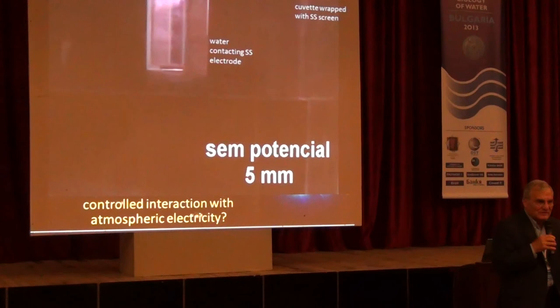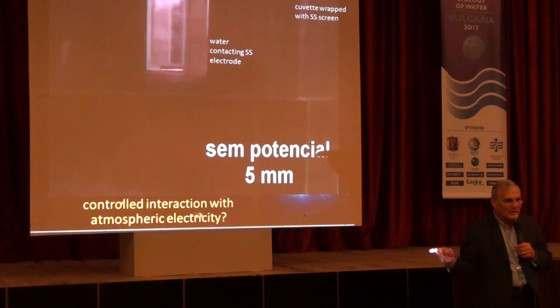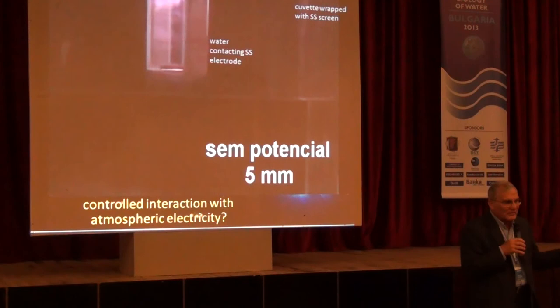So, to conclude, electrostatic charges are really more dangerous under low humidity than at high humidity, because they last for longer. And what we should not do is expose an item to very high humidity and quickly transfer it to very low humidity. Because then you don't give time for the relaxation, and if water absorption is low, we are going to keep charge there.